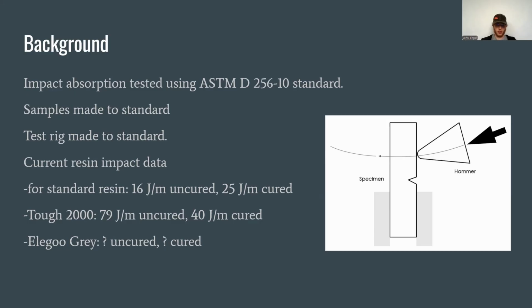Another resin tested by Formlabs is Tough 2000, which has an impact strength of 79 joules per meter uncured and 40 joules per meter cured. As the name implies, Tough 2000 is an engineering grade resin that is designed to be stronger than standard resins. The last resin we tested was Elegoo water washable ceramic gray. We could not find any impact data on the Elegoo resin, and therefore this is likely the first test of its kind.